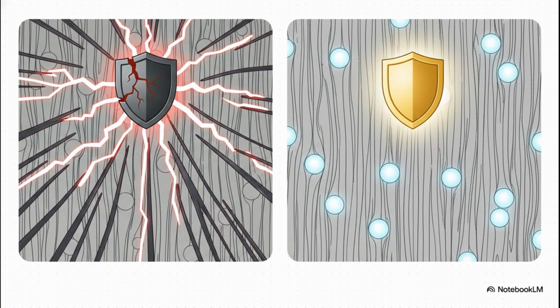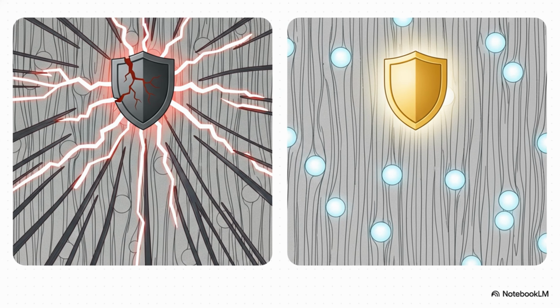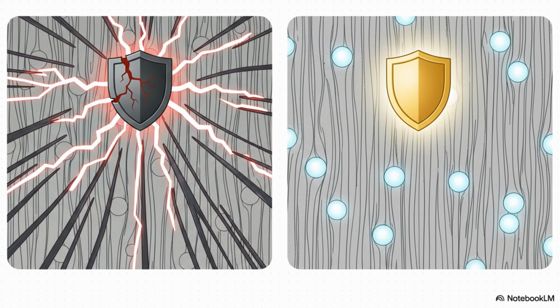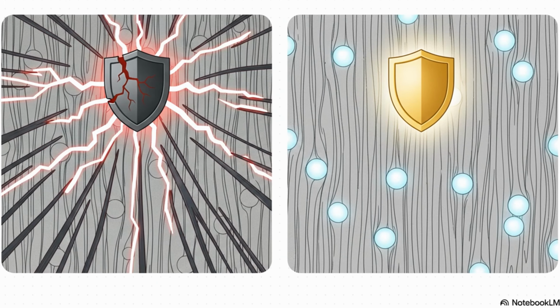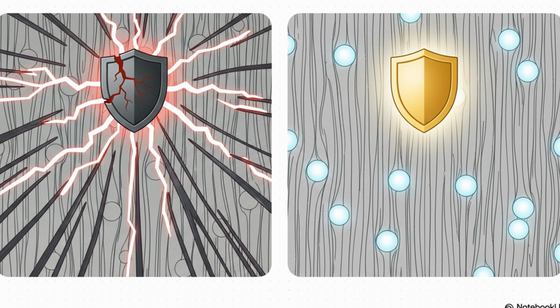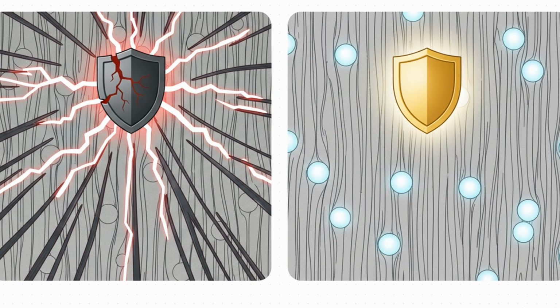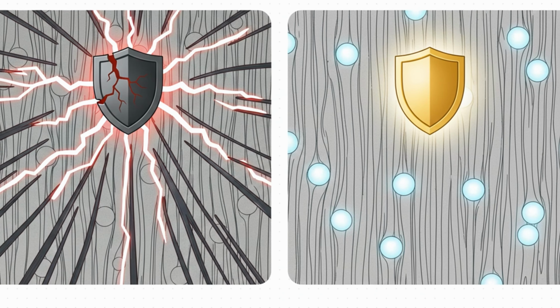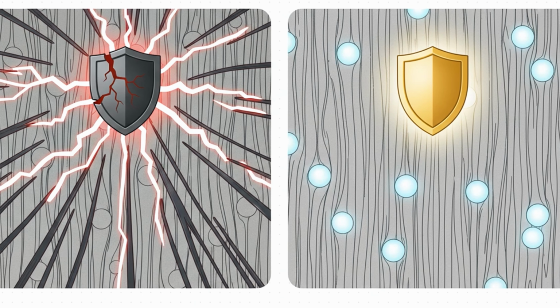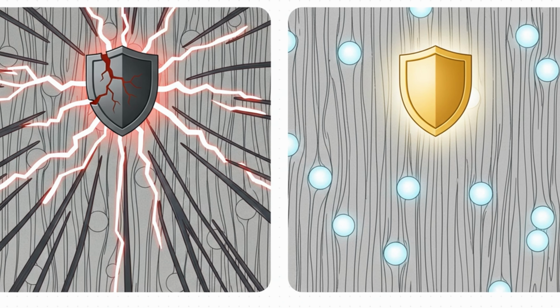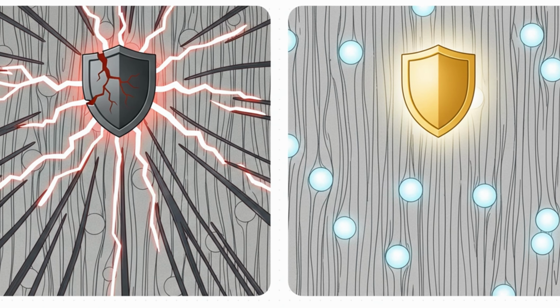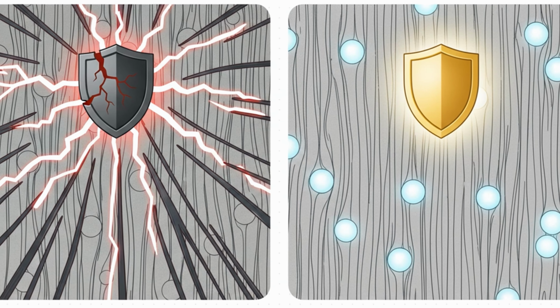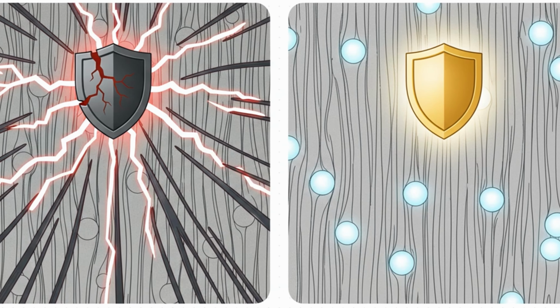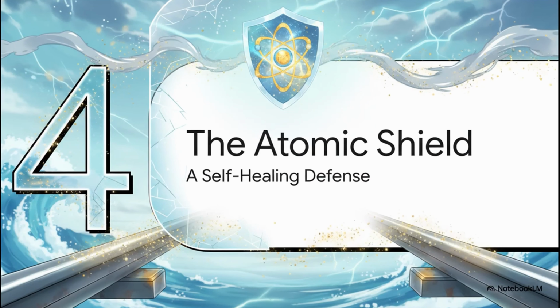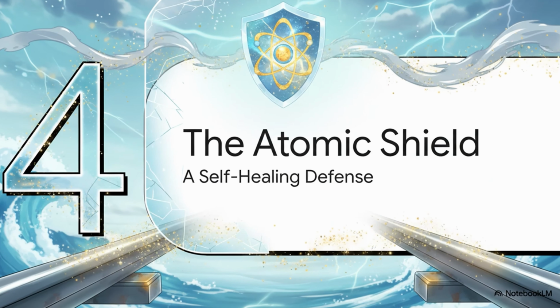And here is where you can literally see the difference it makes. On the left, in normal steel, those soft impurities get stretched out into these long, sharp, needle-like shapes. They're basically tiny internal cracks just waiting to happen. But on the right, with the rare earth steel, look at that. The compounds they form are incredibly hard and stay as perfect little spheres. They don't deform. This keeps the steel's internal structure solid, making it way less likely to crack from the inside. So that internal strength, that's the first line of defense.